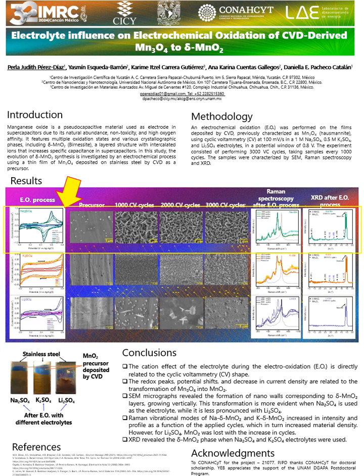Raman spectroscopy confirmed that these nanowalls have the characteristic spectrum of sodium birnessite, especially the bands around 400 inverse centimeters, indicating the intercalated ion in the structure. Furthermore, X-ray diffraction corroborates this birnessite phase at the end of the process, with the 001 plane being the most characteristic.